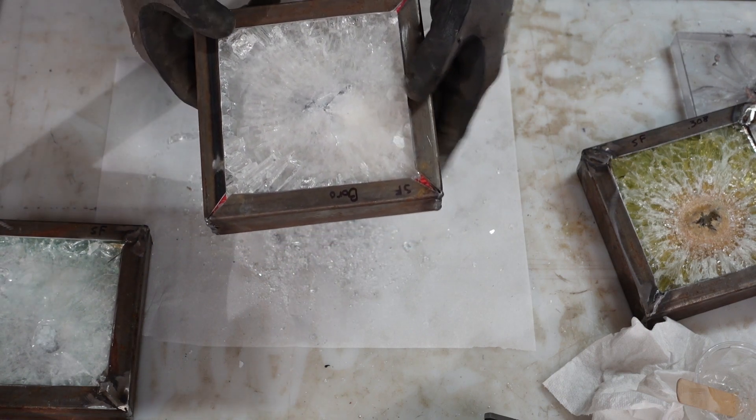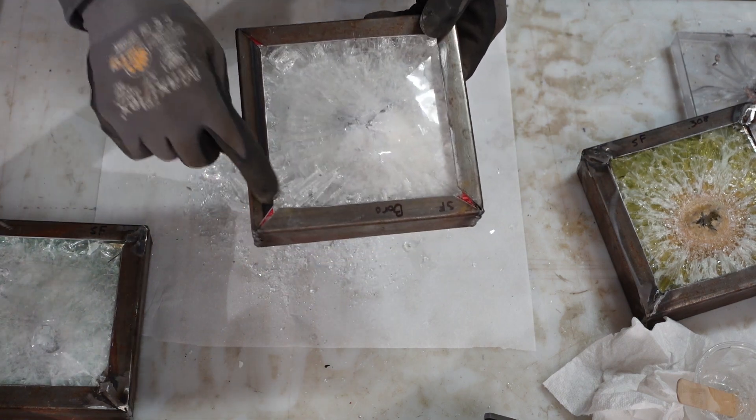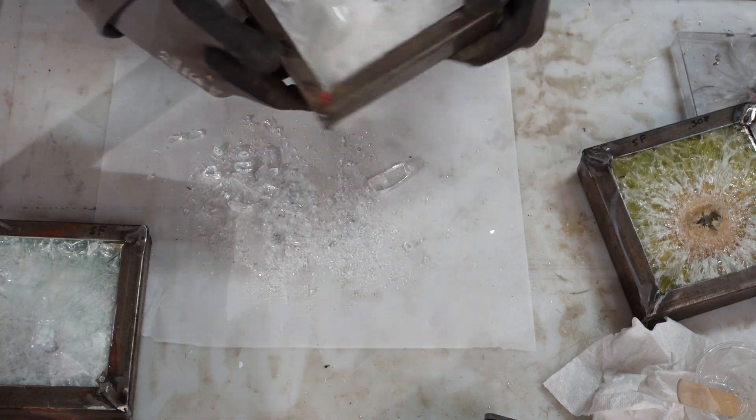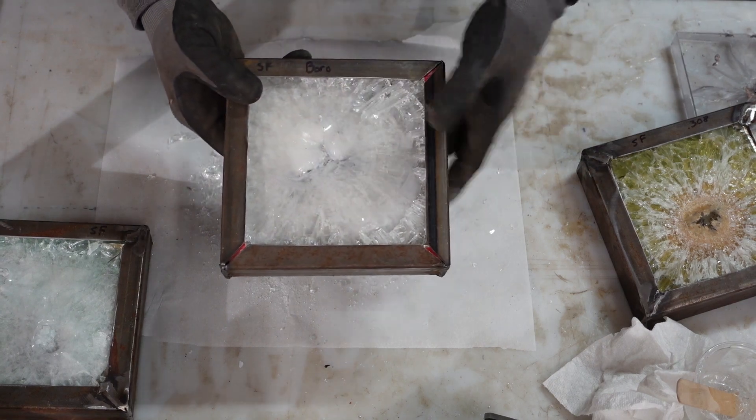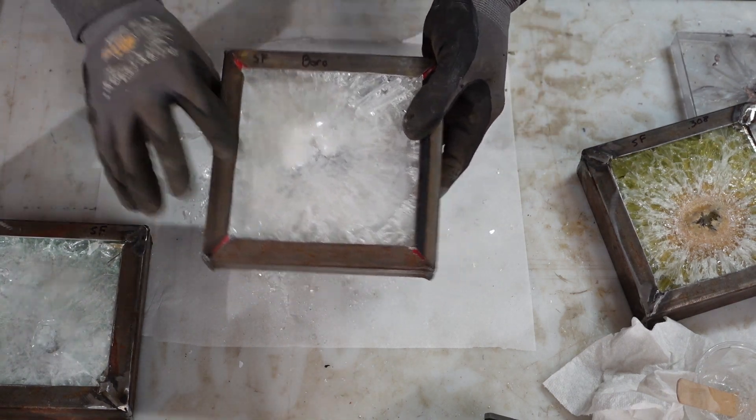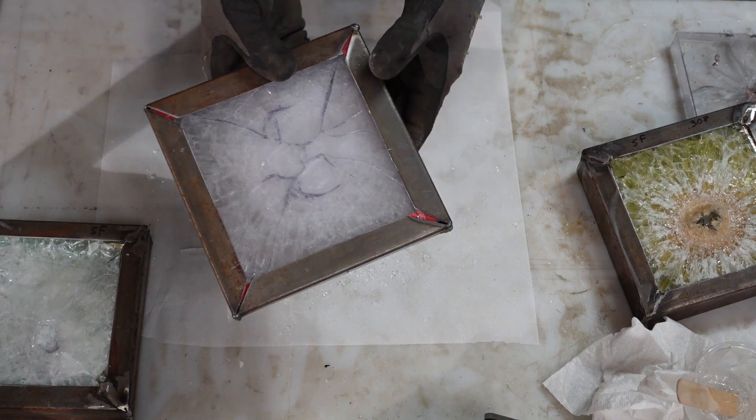It seems to be a little bit more brittle, but it is definitely stronger and the way we can tell is the break up in the back. There was nothing. I really truly believe had we had film in the front of this, this could have taken multiple shots. Definitely worth maybe doing a bit more testing on this borosilicate glass. As you can see here's the 7.62 by 39 and nothing, nothing came through as far as the borosilicate glass.